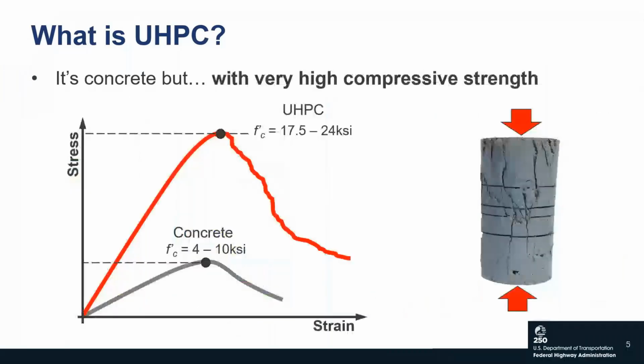In terms of mechanical property, UHPC, again, it's still concrete, but it has a very, very high compressive strength. The picture on the left-hand side shows a comparison between the compressive stress strain curve of conventional concrete in dark gray compared to UHPC in red. As you can see, UHPC is about twice as stiff as conventional concrete, 2 to 6 times stronger in compression, with the compressive strength ranging with a minimum of 17.5 and can go up to 24 KSI with ambient cure. You can go more with different curing treatments.